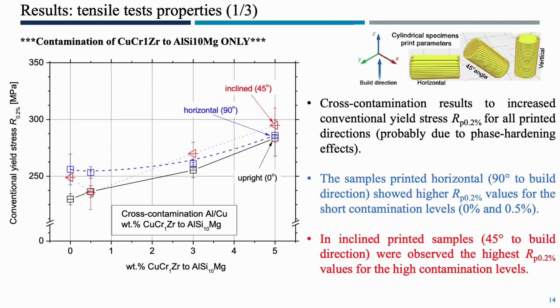And here you can see the tensile test results regarding the different build jobs with different copper contaminations. As you can see, all contamination increase the yield stress. And this is typical because, of course, you have copper addition in aluminum, and there is a possibility to form some intermetallics. That's why you have an increase in yield stress, and of course, the same applies to ultimate tensile strength.